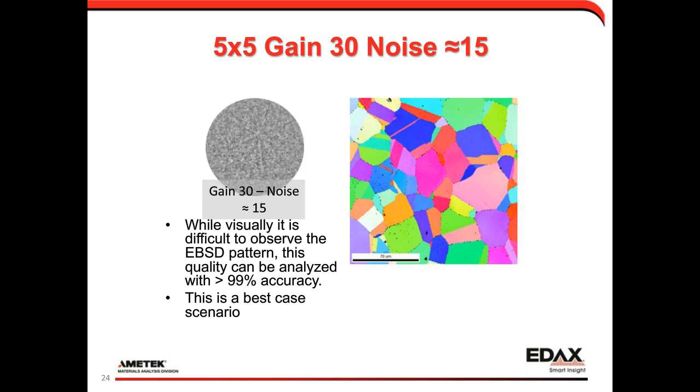Another question says, we only really see what the camera shows. Is there any way to know what the data quality will be before taking scans on a sample? Again, that's where I would use survey mode. Survey mode would let me take a quick point, look at the results, and see if I'm consistently getting relatively high CI and a good fit for the data that I need. Then I can say, okay, let me run a map. The nice thing about this is, if I'm pushing for speed, I can take a map like this in 2 minutes and move on.